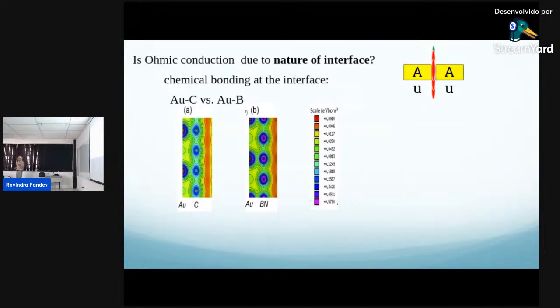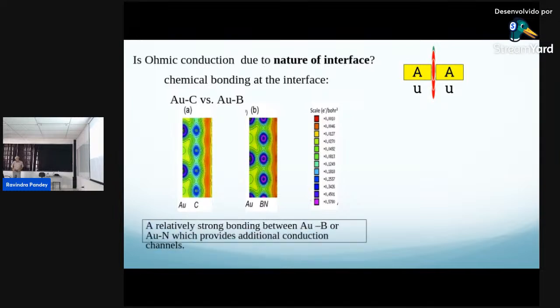So you go to chemistry and look at the chemical bonding. What is going on? That's why we talk about this interdisciplinary nature, because in solid state physics you don't care about the bonding as such, but we are looking at nanomaterials. The chemist friend told me, Ravi, boron is an electron-hungry atom. It loves electrons. You can see the gold-boron contact shows a large overlap relative to the gold-carbon contacts. So boron or carbon, they love to form bonds with gold. The interface is taking over the material's intrinsic property. That's the message coming out. So what we have is strong bonding at the interface, which provides an additional conduction channel. That's why we have ohmic-like or metal-like conduction.